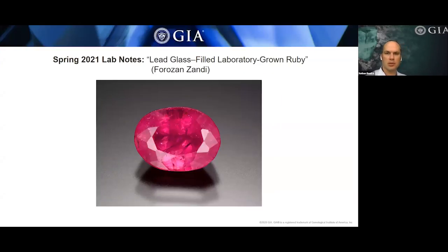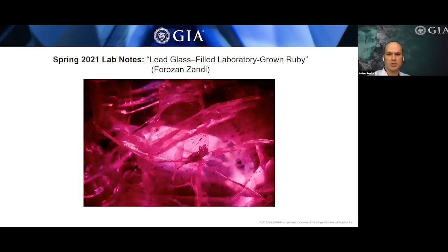Also in the lab notes in Carlsbad, we examined a lead glass filled lab grown ruby. Now you may be wondering, why would anybody lead glass fill a lab grown ruby? I'm not sure that I have the answer to that, and we were surprised at seeing this as well. Internally, the stone had numerous glass-filled fractures. You see trapped flattened gas bubbles in those fractures, and the glass filler lies within those. There was also some flash effect observed.